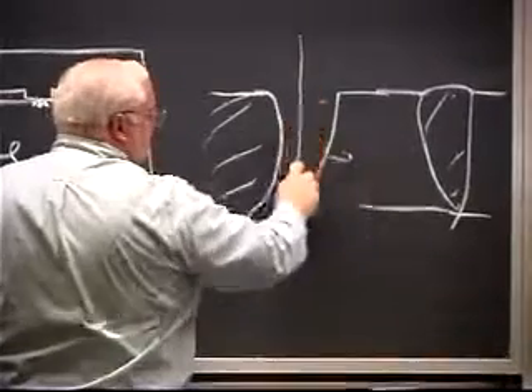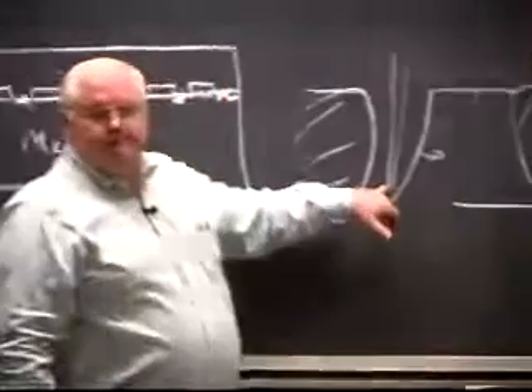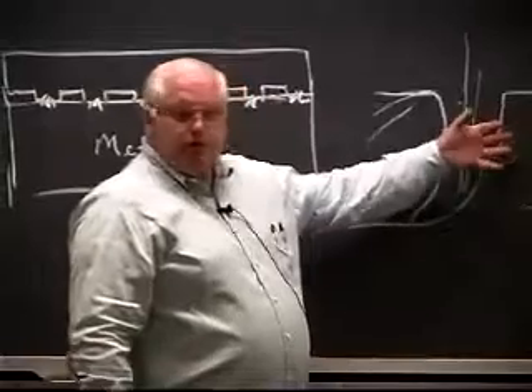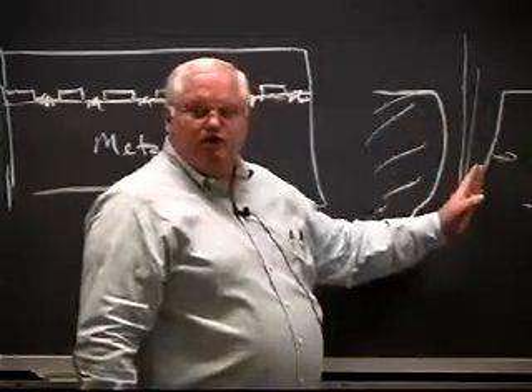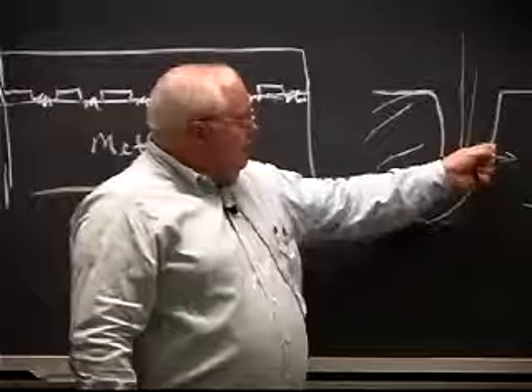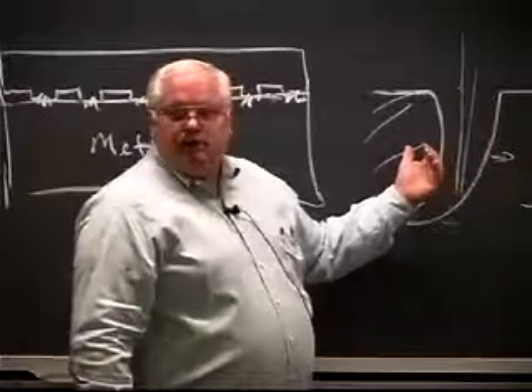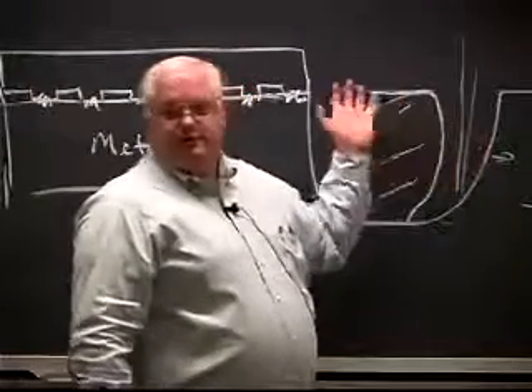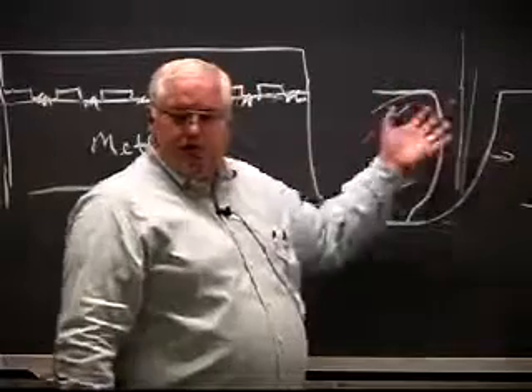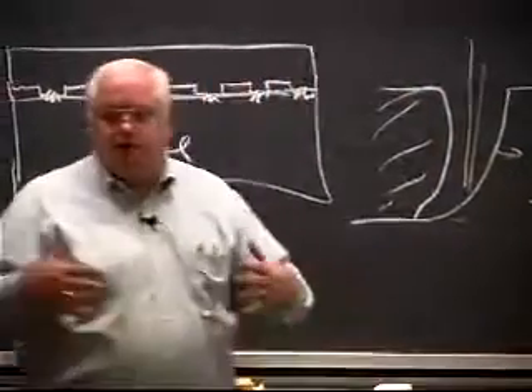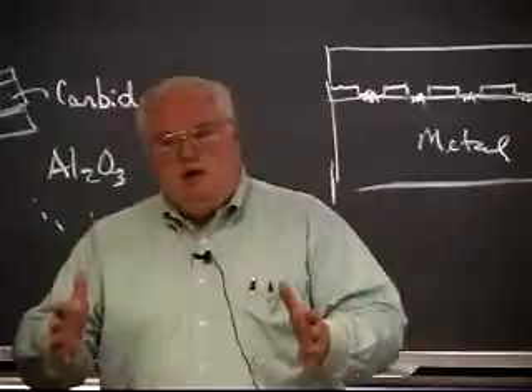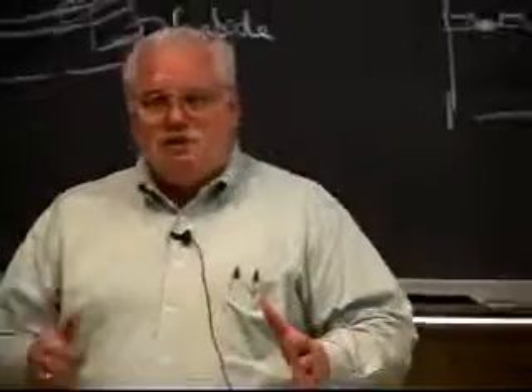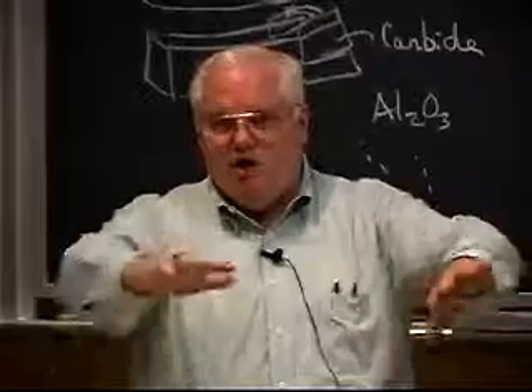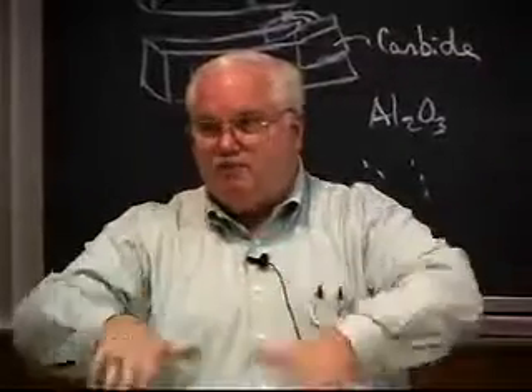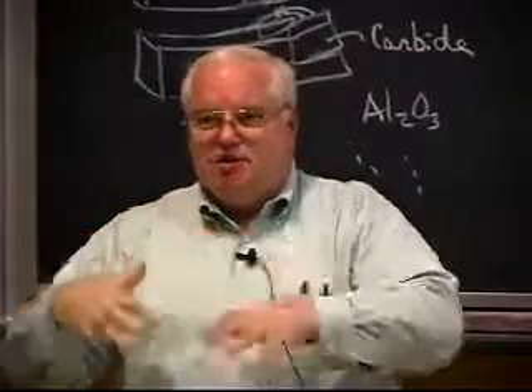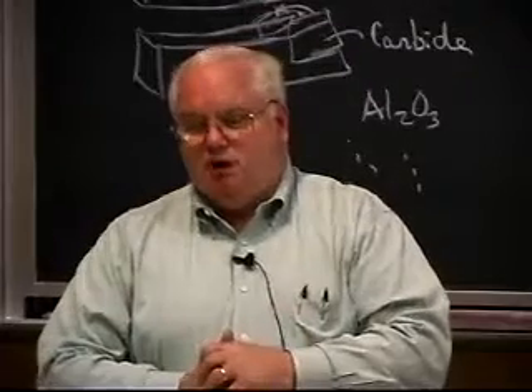And the beam actually drills a hole in the material. And you have fluid flow that sweeps around. So you're melting the front wall as you're moving forward with the beam. And the fluid flows around and solidifies in the back. Well, as it does that, it creates certain types of defects if you're not careful back here, depending on the fluid flow. I like to liken it to a motorboat going through the water. If you've ever done water skiing, you know as you go faster and the boat starts plowing through the water, you get a wake in the back of the boat where you have depressions and you have humps. Well, you're going to see the same types of humps in the electron beam welds,